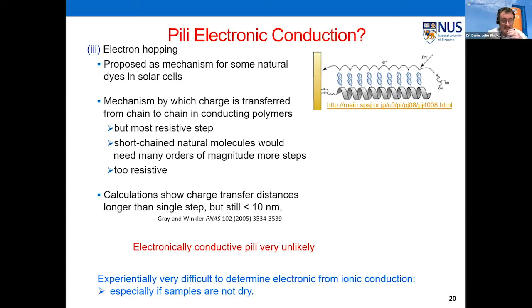One of the problems is it's actually experimentally very difficult to determine electronic from ionic conduction, especially when your samples are not dry. A lot of the work I've looked at on this, it turns out that if you do a comparison of the conductivities that are claimed for these pili, it usually turns out to be pretty close to the conductivity of seawater, which always worries me, right? So you're claiming an electronic conductivity, which is basically the same as the ionic conductivity you'd expect for the media that you've been working in.